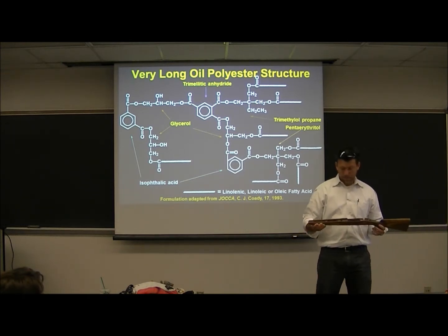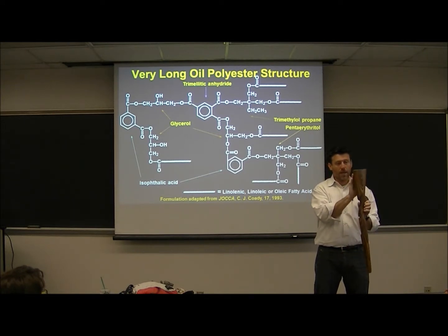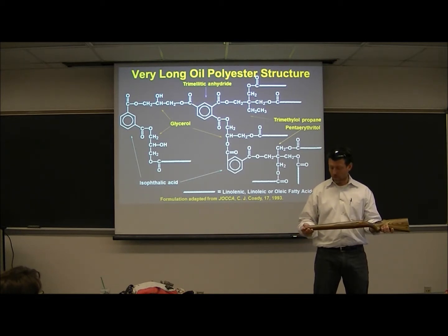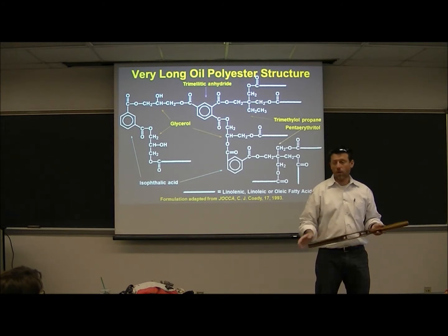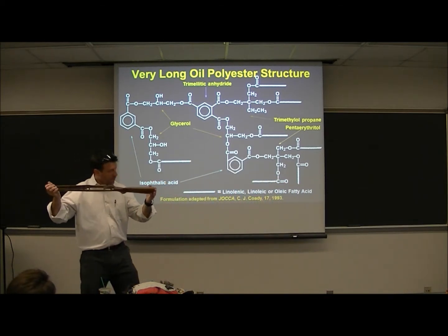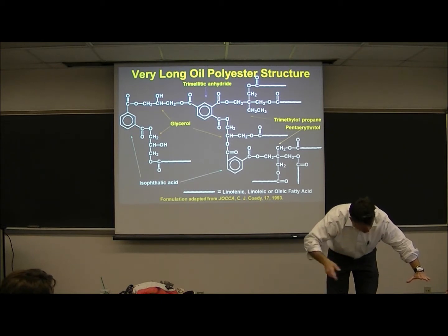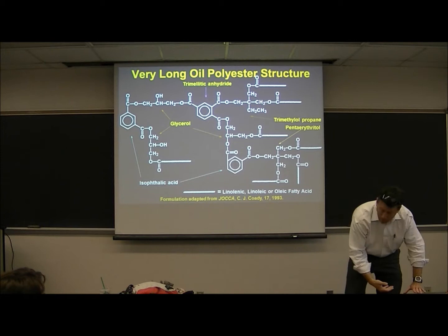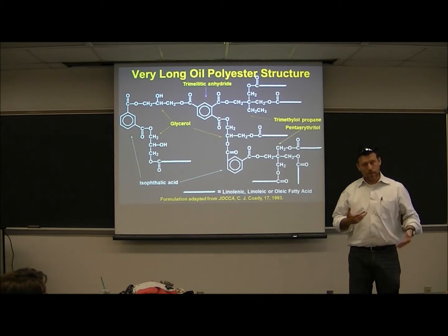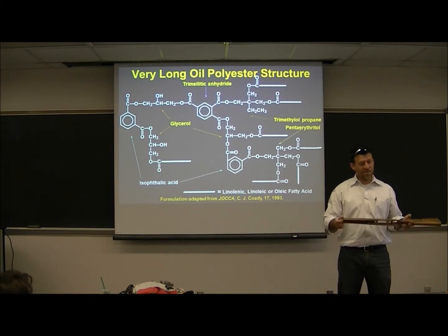This is an interesting thing because this is a laminate, and it's a well-made one. I can't remember the company's name that we did the work for, but it's a well-made. This is for a Remington 700, for those of you that have rifles, and it's chipped. Otherwise, it would be on one. But it's a good example. So what I want you to do is look down inside here. What we did is we took this stock and we put it into a pipe. And we filled the level of liquid above that, and then we pulled a vacuum for days. It took days the first time we did it. It pulls all the air out, and when it pulls the air out, there's a porosity that needs to be filled in because it's below the liquid level. The liquid keeps seeping in. It's the low viscosity liquid. It seeps in. So we actually, for lack of a better word, impregnated this with resin.